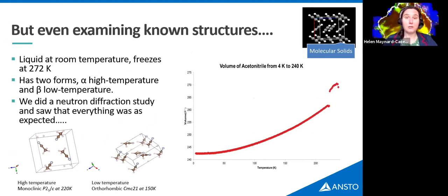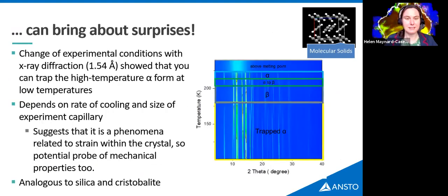But as I said, even for known crystal structures, so acetonitrile is probably one of the most used solvents in any lab, and there are numerous crystal structures in that database where it's there as a co-crystal, or it's there as a co-former as well. But we looked at it pure, and again, they already knew the crystal structures of it, monoclinic and orthorhombic. We did the neutron. Neutrons are generally with bigger samples. Everything was kind of expected. But when our honours student, James, went to do it on the X-rays with a smaller capillary, he found that as he cooled down, he actually got the high temperature form persisting at low temperature. And then when he warmed up, he would get the low temperature form, and then he'd get a mixture of them all. And so what he discovered was that actually we've got the potential of phase trapping.